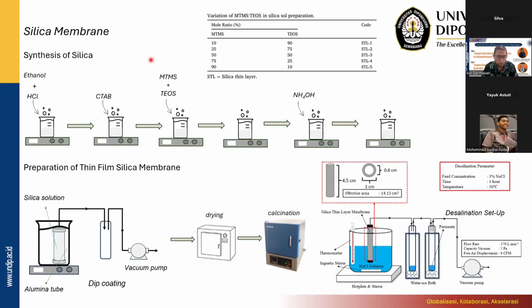So we have to combine TEOS with MTMS. Because of the methyl groups in its structure, MTMS can make the structure more organic, or more hydrophobic. Here you can see a table of the composition between MTMS and TEOS. First, the majority is TEOS at 90% and only 10% MTMS, and then the MTMS content increases while the TEOS content decreases.